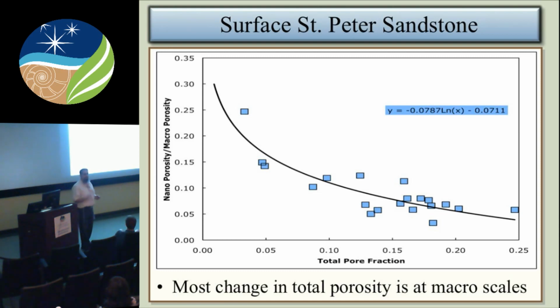Okay. The same thing, interestingly, was seen in the St. Peter sandstone at the materials that were at the surface. The smaller pores, again, were what filled first. So this one has nothing to do with compaction. This is simply precipitation. That's a silcrete formation. Same thing happened. We got the smaller pores filling up first.